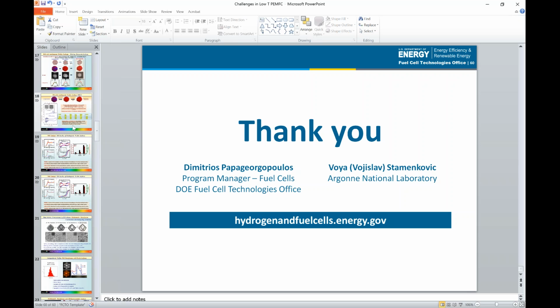Have you looked at the activity and durability of the novel catalyst structures at higher temperatures, let's say 150 to 300 Celsius? That high was not considered, but we definitely consider the temperature range which is relevant for MEAs, so going up to 80 C. This is something that we usually do, but 150 and 300, no, except looking into so-called thermostability, whether this frame structure is going to collapse, whether it is going to survive after exposure to 300 degrees, and basically we confirmed it can survive up to 350 or so.